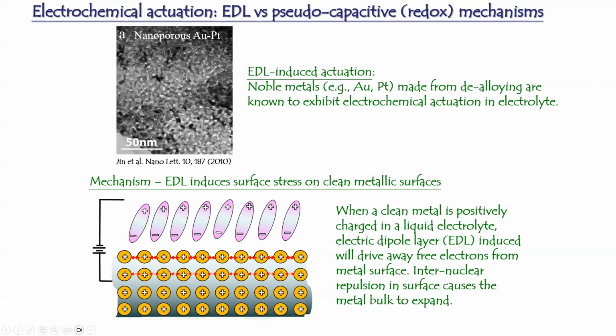So let's say if you charge the material positively, the positive charge here will induce these dipoles in the electrolyte. So the negative ends of the dipoles will point towards the metal. And once this is done, the positive parts of the dipoles will drive away the free electrons in the metal. So the first few atomic layers in the metal will now be depleted of electrons. And therefore, the positive nuclei of the metal will repel. So this is a very simple actuation mechanism that has been demonstrated for clean metallic surfaces.